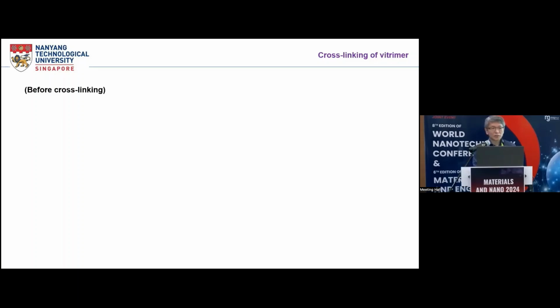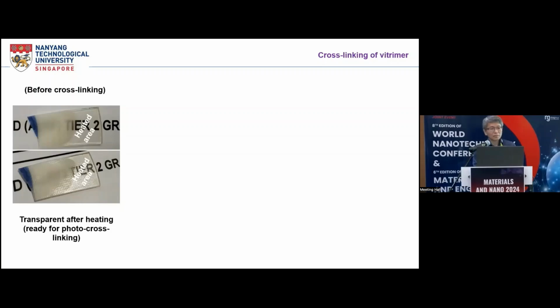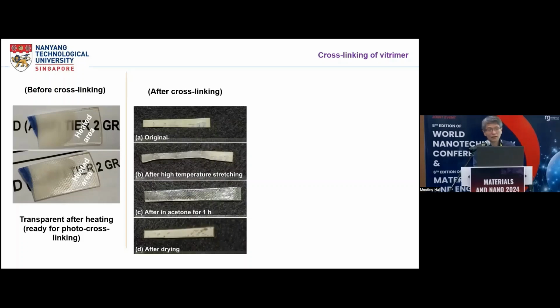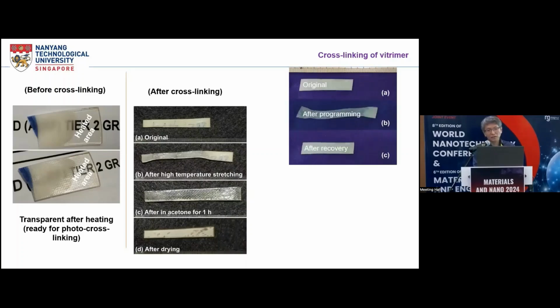We need to make sure that the material is transparent. So we heat this part of this vitrimer, and we can see it changes from translucent to transparent. So of course, this is very good for UV cross-linking into the material. And the second, as I previously mentioned, is about after cross-linking, whether the material has a shape memory effect. Yes, the material has a very good heating responsive and chemical responsive shape memory effect. Heating responsive means that upon heating, it's able to fully recover its own shape. And chemical responsive, for this particular material, we use acetone. Of course, this is not an eco-friendly method for shape recovery. We simply use this to demonstrate that it has an excellent shape memory effect. So yes, the material has an excellent shape memory effect to ensure accuracy of the produced item.